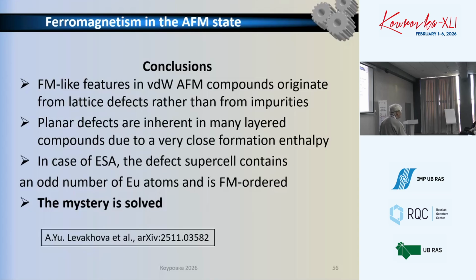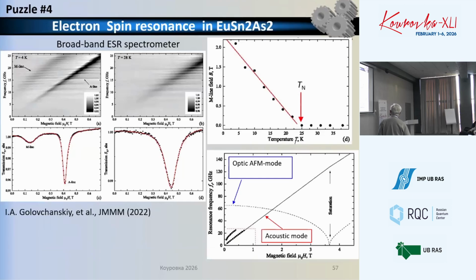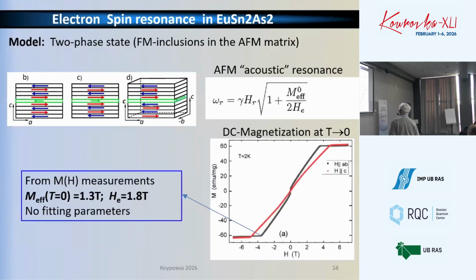And let us test how it may be pronounced in measurable properties. So we turn back to our measurements of the electron spin resonance, which we did in 2024, and we observed in this same material, instead of one resonance line, two resonance lines. This is typical for antiferromagnets, and this was completely unclear. So we couldn't understand the origin, and we only concluded that this has nothing to do with the optical antiferromagnetic mode. And now we apply the naive model of a ferromagnetic planar defect embedded into the bulk crystal, and try to understand this behavior.